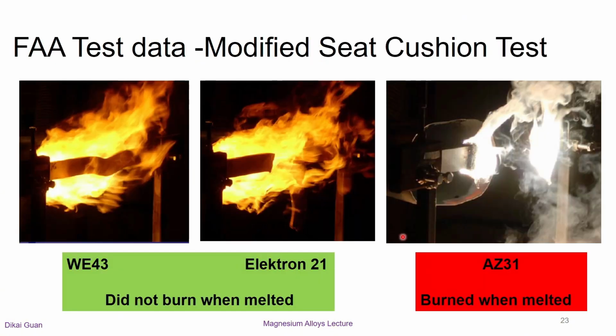While magnesium products have been used in military aircraft for many years, they have had little use in civil aircraft interiors due to flammability restrictions from the U.S. Federal Aviation Administration (FAA). In 2013, the results of the magnesium full-scale testing and the progress demonstrated in the development of the lab-scale test method led the FAA to announce that it would now allow magnesium in aircraft seats.